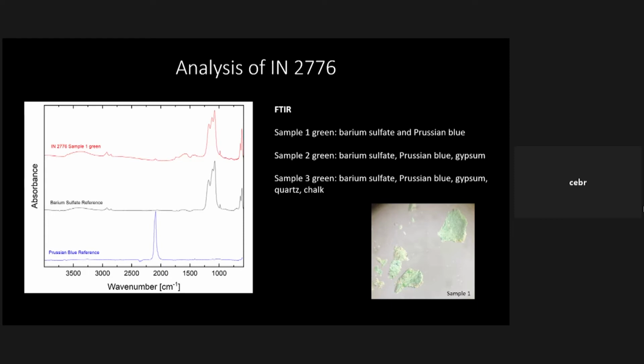Moreover, the XRF shows zinc, barium, and sulfur, suggesting the presence of the dense white pigment lithophone, which is composed of a mixture of zinc sulfide and barium sulfate, with trace amounts of zinc oxide. Lithophone was first produced in 1874. Lithophone is an inert, transparent pigment, which is often used as a filler or as a base for lake pigments. It was widely used in house paints in the first half of the 20th century.